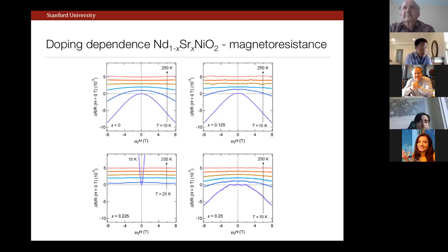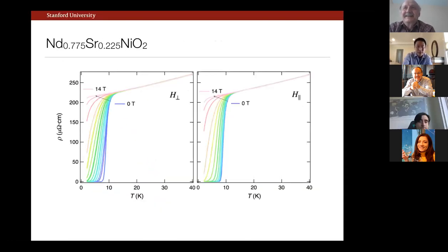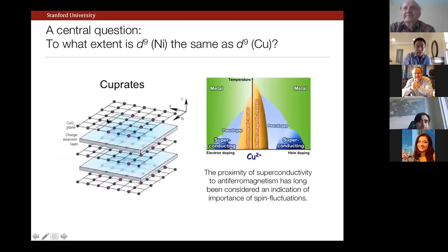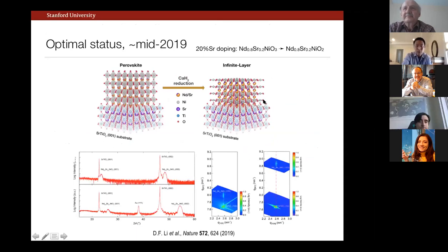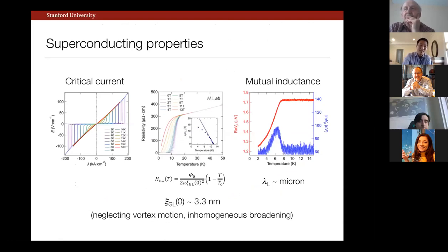Okay, so certainly based on my past, I must believe that that's important. So let me just say, what's a good picture? So what Mark is pointing out is that if I do a naive count, this will actually be +3, -3 layers. So I have the same electrostatic problem, or actually even a worse one with the interface with strontium titanate. So what's going on? I should say that there are at least a few papers, electronic structure calculations worrying about this in detail. I would say two things is my best answer right now. One is I feel reasonably confident that it has to be a bulk effect across the film, in the sense that the critical current densities, as I say, we're now getting up towards 400.